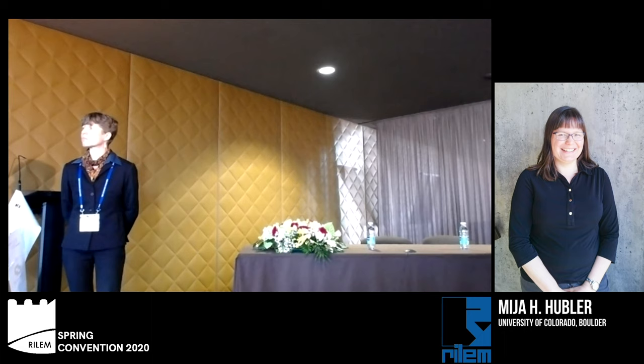One of the things that I enjoy doing as an engineer is making approximations. And I think that's very important if we want to introduce something like this into design. The reason, in part, why there are so many parameters, for example, in our existing creep and shrinkage prediction equations is because probably the crack network statistic is related to the water cement ratio. Probably the crack network statistic is related to the strength of the material. So we have all the information there. It's just not as directly related as possible.